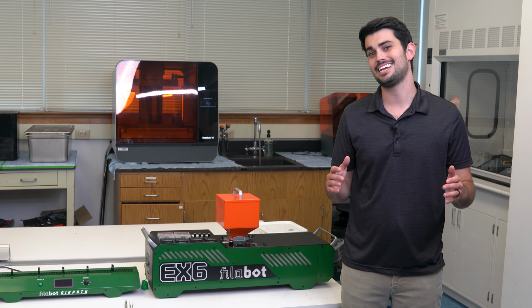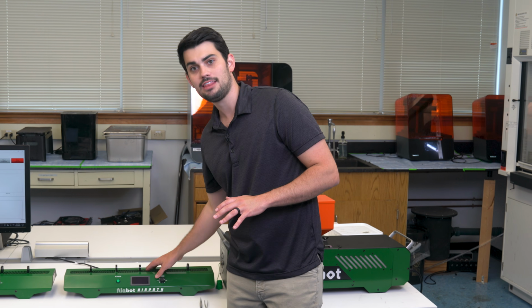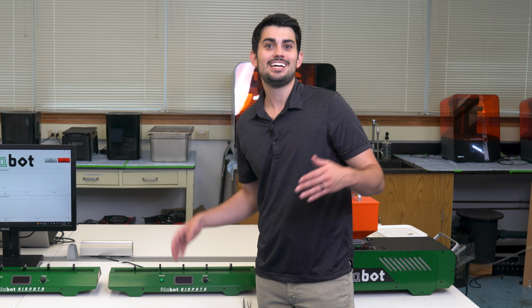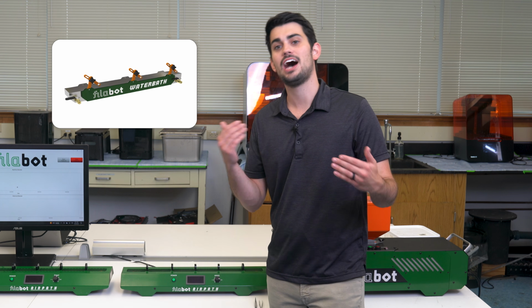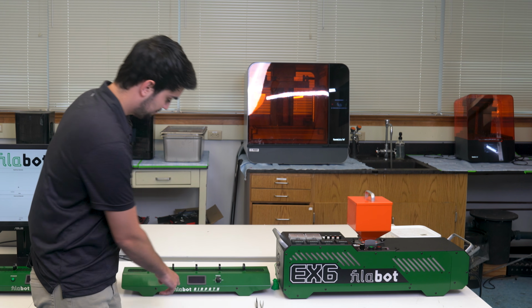The molten plastic can be air or water cooled. Filabot sells both an Airpath, which uses fans to cool the newly extruded filament, and a water bath, which of course uses water. For fast extrusion speeds, the high cooling capacity of the water bath will be necessary. The Airpath, which I have, is easier to set up and requires less maintenance, but it is a little bit loud.